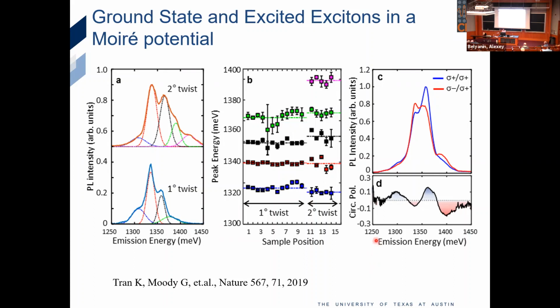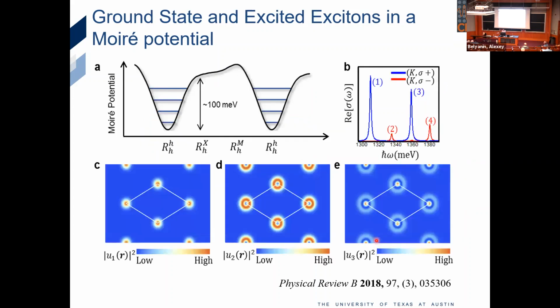Okay, other questions? All right, so just to throw in another possible interpretation, maybe the excitons are not sitting at different locations of the Moiré supercell. Instead, there's a global energy minimum, but because the energy trap is sufficiently deep, I can actually have a ground state and excited states of the exciton. And these are the calculated center-of-mass wave functions. And these are the calculated absorption spectra that say, even if they're localized in the global minimum in the Moiré potential, I can confine more than one state. They will also have this alternating selection rule. So again, this is something we don't know. We don't have the experimental tool to rule out one explanation versus the other. Our own paper picked this interpretation because of some other supporting experiments, temperature dependence and lifetime measurements, but I won't bore you with those details. Just know that we're just getting started to understand this optical excitation in the Moiré superlattice.